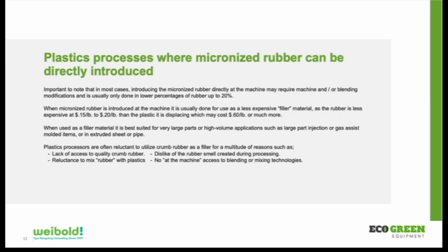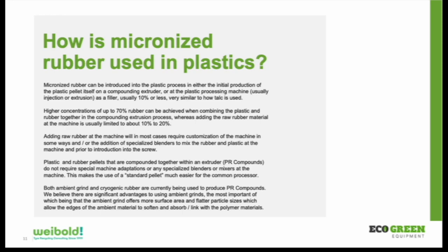So, how is micronized rubber used in plastics? Well, the micronized rubber can be introduced in the plastics process either in the initial production phase or into the plastic pellet phase, which is where we're compounding in an extruder. And what I mean by that is if you're introducing it into, say, just an injection molder or a blow molding machine, you can mix it into the mixing stations that they have at the machines, and they can do that more as a filler. So generally, you're doing it at up to about 10%, and basically what you're doing there is you're offsetting the cost of the plastics. So a good example would be back when I was in the plastics industry in the 90s. Plastics prices did what they're doing now because they kind of follow oil, and they would go up very high in cost, and people would look for ways to offset plastic cost.